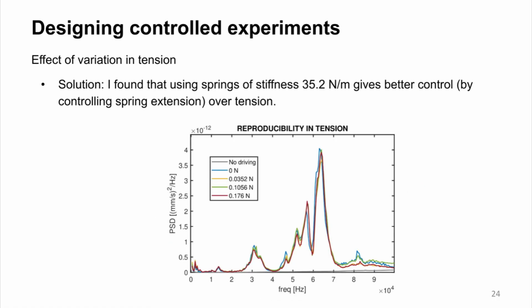So to control the tension and achieve reproducibility across measurements, I found that using a spring of 35.2 newtons per meter gave me good enough control over tension by controlling the extensions in the springs. And if I vary the spring extension over a few millimeters, 0 millimeters to 5 millimeters, I find that I get roughly the same curve. So my control over tension now is better than the sensitivity of the metamaterials to the tension.